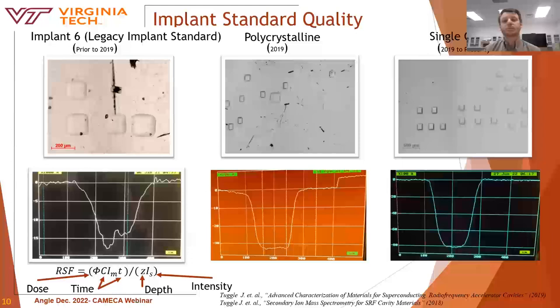Reconsidering the RSF equation, many of its terms are difficult to assign an uncertainty value. However, the uncertainty of the crater depth can be attained and is evident from the crater profiles. We assumed that the uncertainty in crater depth measurement would propagate to the RSF equation. Therefore, we sought to avoid this issue by analyzing larger grain polycrystalline samples, which could somewhat avoid the uncertainty resulting from rough crater bottoms.